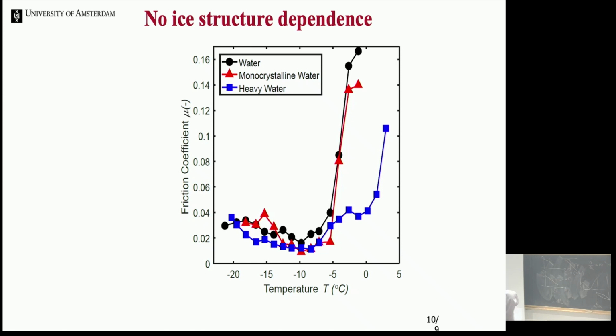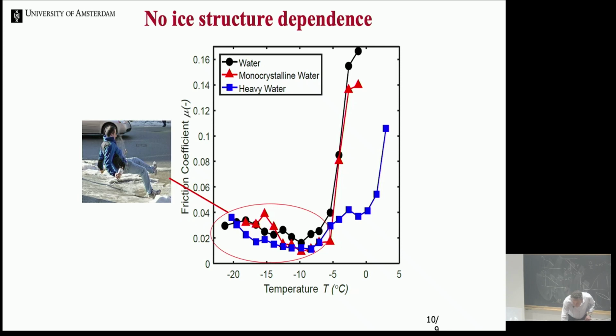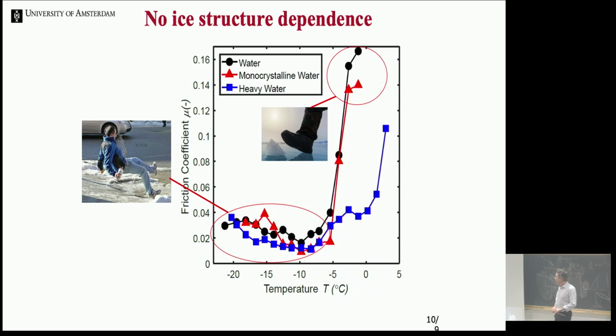Yeah, so we have two setups. We have a Peltier that will cool the bottom, and that is very nice if you're in this region. But if you really want to go low, we use liquid nitrogen, and so we have a closed system with the rheometer axis going in, with liquid nitrogen flowing through a metal plate at the bottom of which we make a metal cup, sorry, at the bottom of which we make the ice. Yeah, and so there's a region where you will fall, but if it's too close to 0, you will actually not fall. And that I think we all know, and that's going to come back in the measurements.